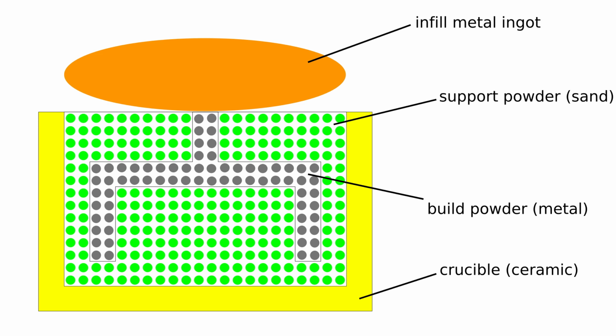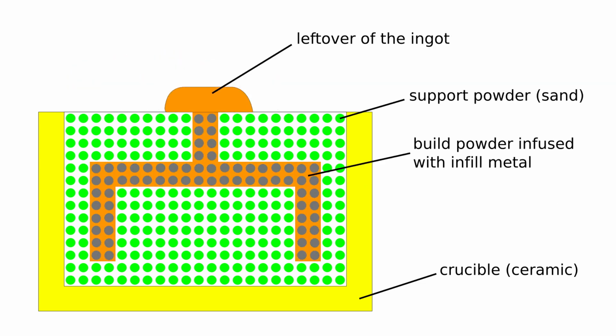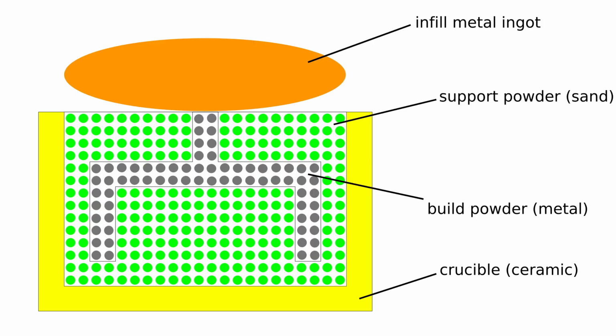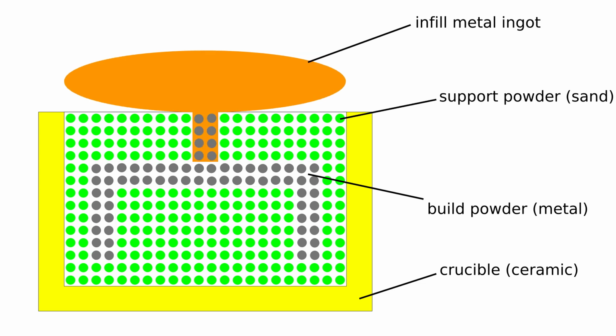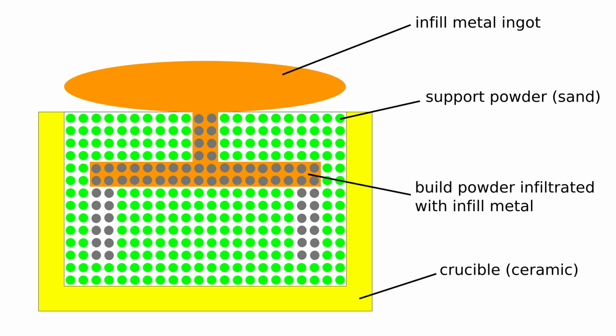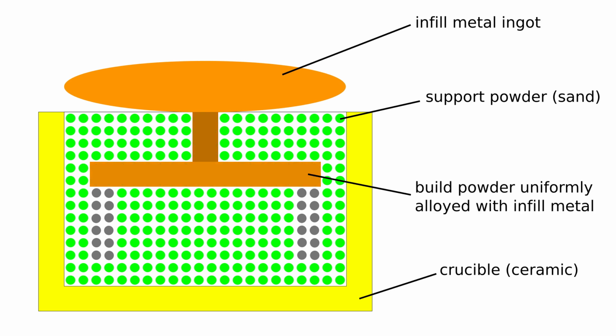This works fine when the crucible is small and warms up quickly, and the infill metal melts quickly. And when our powder and infill atoms diffuse slowly, like tungsten and copper, then it works fine. But when our crucible is large and warms up slowly, and the infill metal melts slowly, and when our powder and infill atoms diffuse quickly, like copper and tin, then the powder may get infilled incompletely or unevenly.